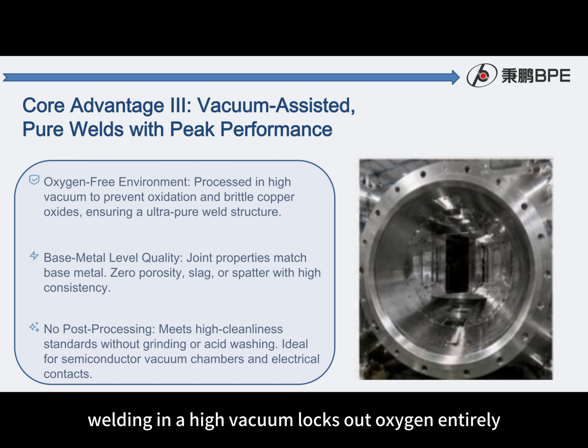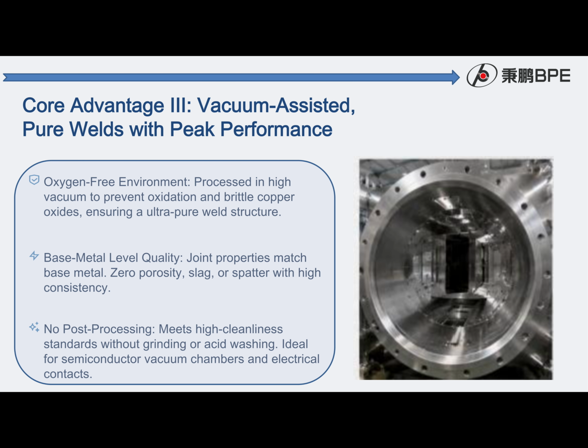Welding in a high vacuum locks out oxygen entirely. You get clean, oxide-free joints that match the parent metal in strength and conductivity. There's no spatter, no slag, no porosity, and no need for post-weld acid washing, perfect for ultra-clean electronics and vacuum devices.